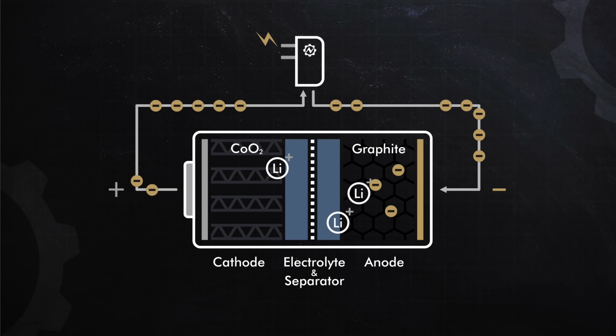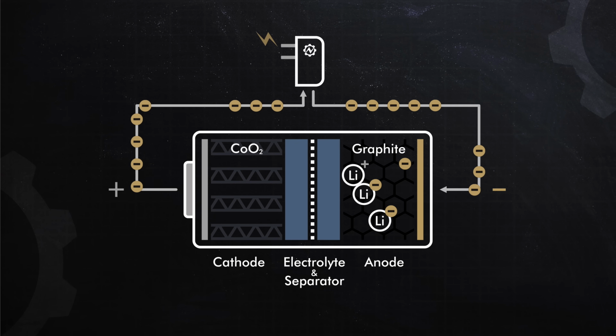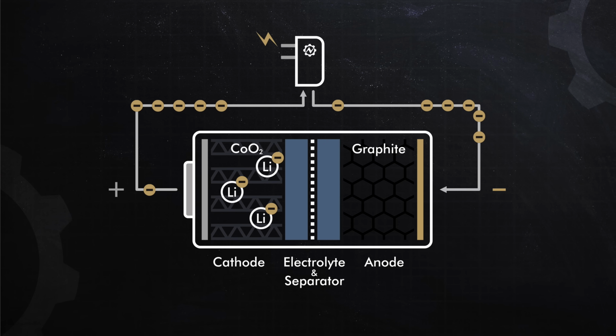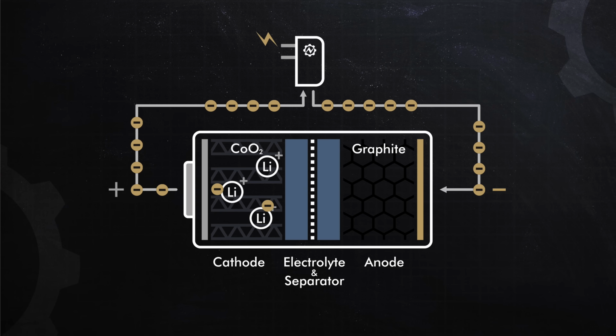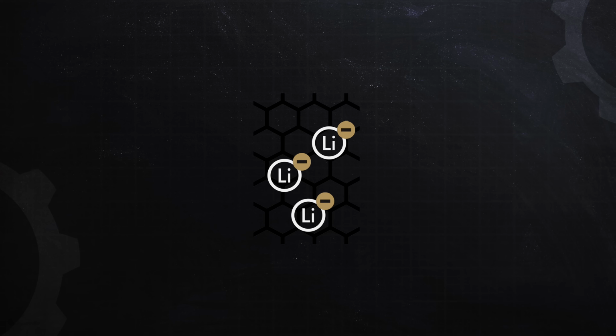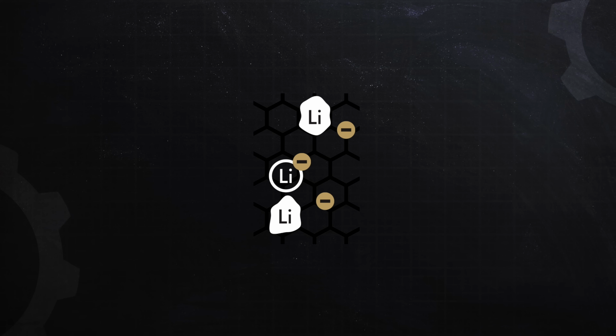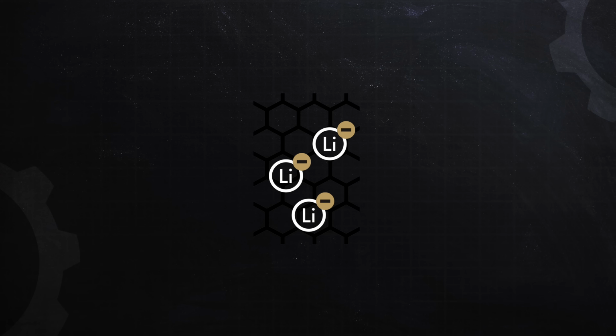The second mechanism responsible for cyclic aging is lithium plating. Lithium plating primarily occurs at the anode during charging. The higher the charge rate, the greater the number of electrons that are being driven from the cathode to the anode. As the electron flow increases, so does the flow of lithium ions across the separator. These lithium ions have to be received into the graphite matrix to balance their charge with the electrons. And the problem here is that the graphite has a maximum rate at which it can accept lithium ions. If this rate is exceeded, the lithium ions begin to build up on the anode. Ideally, when the charging stops, the lithium will deplate and work its way into the anode. However, there can also be reactions with the electrolyte, and this can form some permanent surface films on the anode.